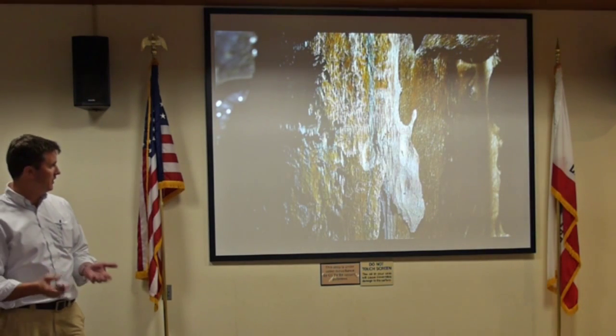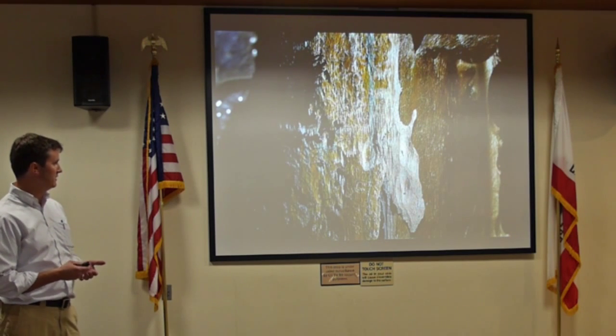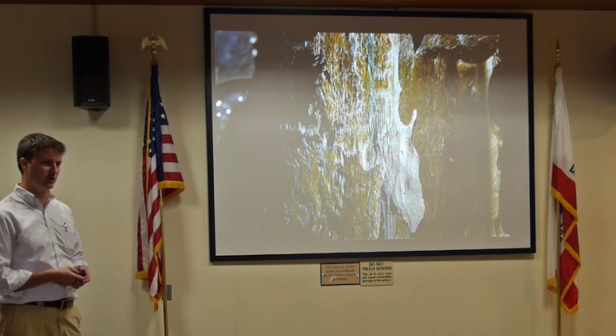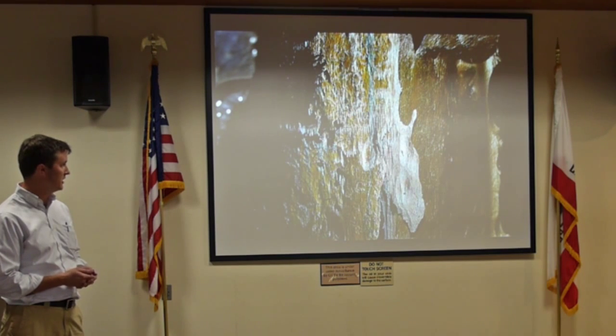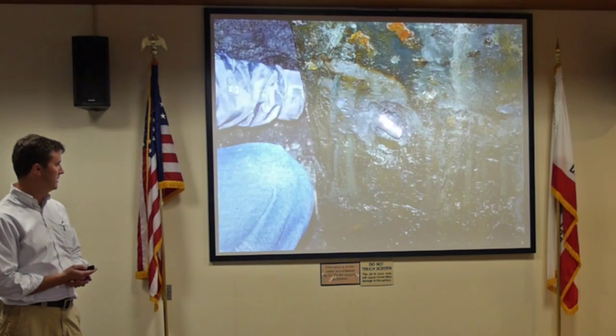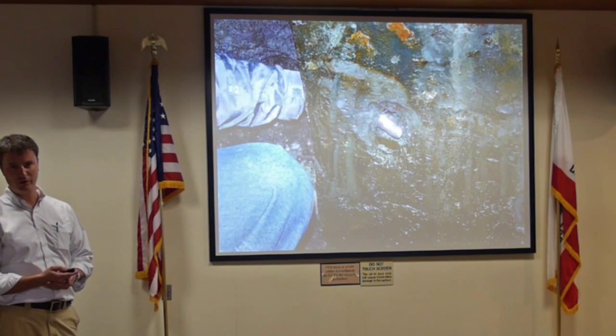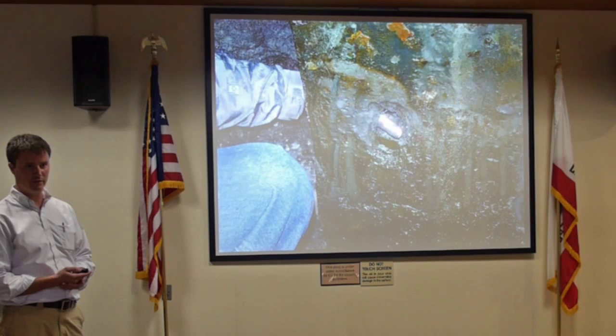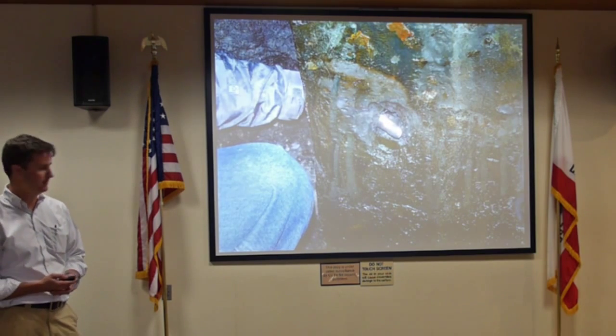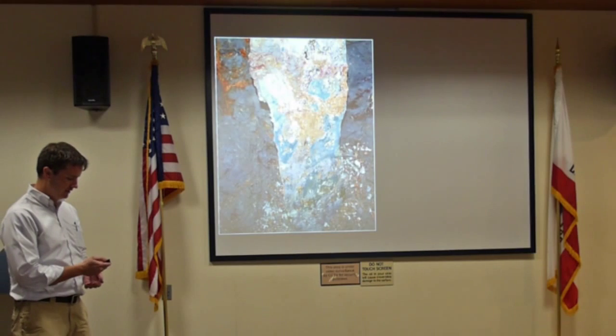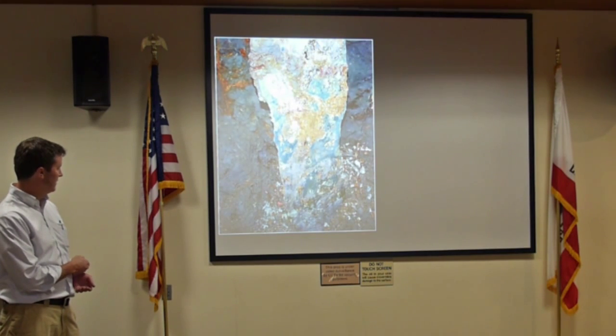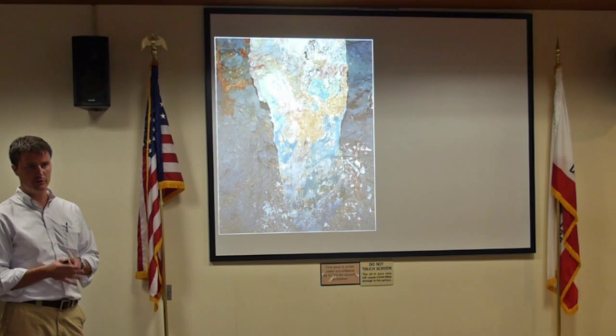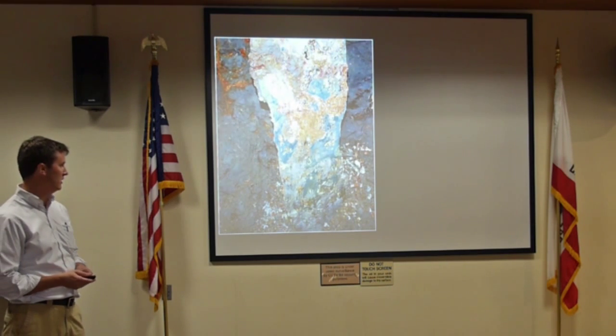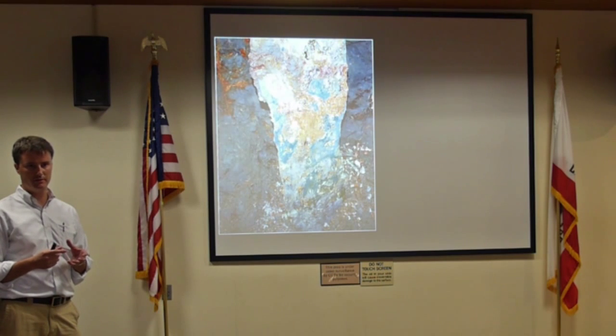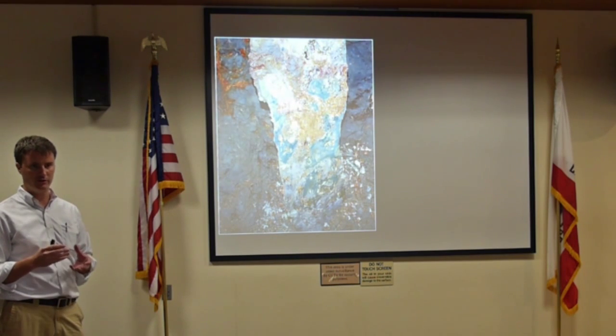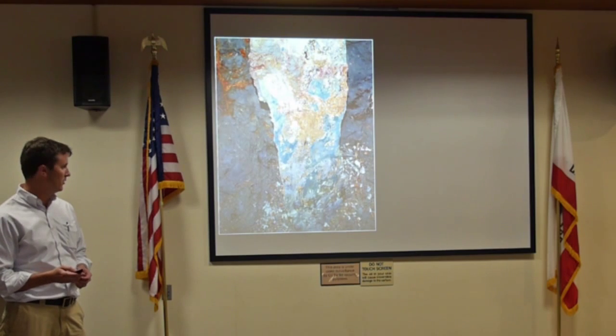The other thing is a very interesting type of corrosion. It almost looks like wood. You have these longitudinal striations in the steel H pile, and you see the section is substantially diminished, to the point where in some local areas you can actually put your finger through the flange. So it's pretty startling to see. You can see again, just on the flange edges, this is almost like a knife edge condition where you just lost so much material that it has gone down to zero along the edge. And at some point, you had lost enough section modulus that it could no longer support the intended loads.